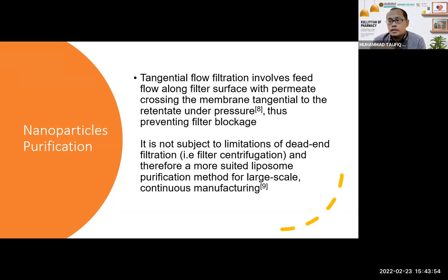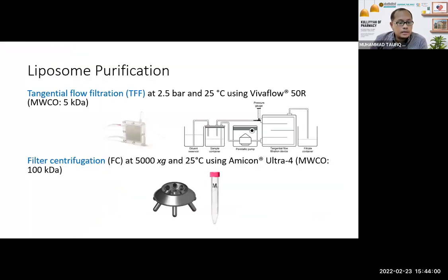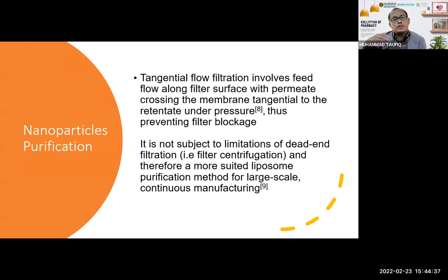So basically, all the non-liposome material will fall down into the tube. It looks something like this, with the centrifuge tubes at the bottom there. There's a small filter in there, and you put all the sample on top, you run it in the centrifuge, and all the excess liquid will fall down. But then again, this doesn't answer the first and foremost problem, which is how can we make this continuous? That means, how can we connect from the manufacturing side, the fabrication using microfluidics, all the way to the purification process?